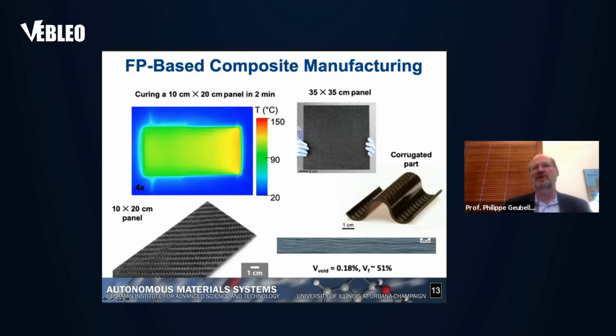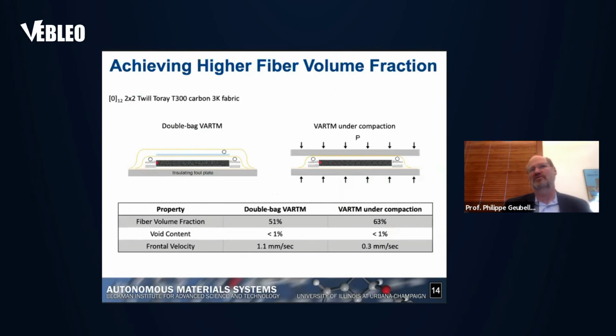Now, if we want to apply it to very high performance applications, clearly we need to go to higher fiber volume fractions. And so instead of using the traditional double bag vacuum assisted resin transfer molding process, we actually adopt a VARTM, but under compaction. So that really allows us to reach higher fiber volume fractions, all the way to 63. I think since then we've gone to even a bit higher. The void content remains very small, so it's still very good quality parts that we create. The front velocity, however, decreases as we increase the fiber volume fraction, which once again makes sense. And I'll come back to that a bit later.